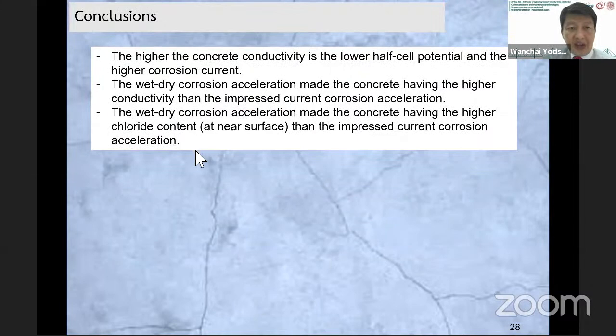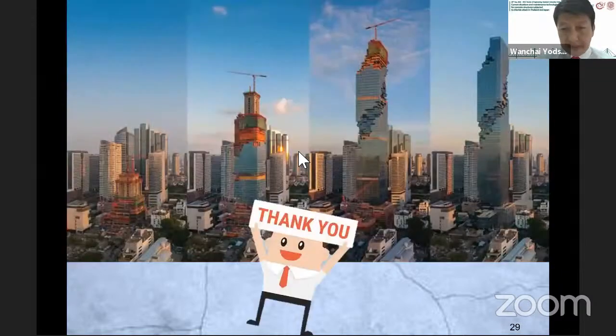So I would like to have the conclusion that the higher the concrete conductivity is, the lower the half cell potential, and the higher the corrosion current. The wet dry corrosion acceleration made the concrete having the higher conductivity than the impressed current corrosion acceleration. And the wet dry corrosion acceleration made the concrete having the higher chloride content at near surface than the impressed current corrosion acceleration. I would like to thank you very much for your kind attention and finish my presentation.